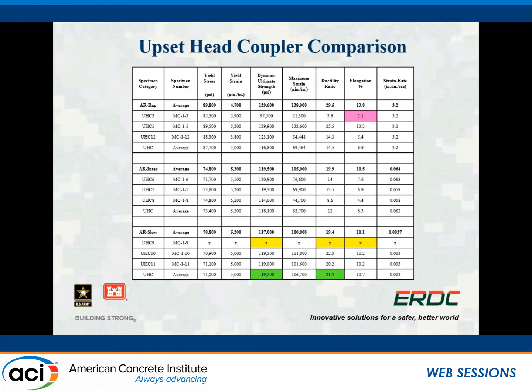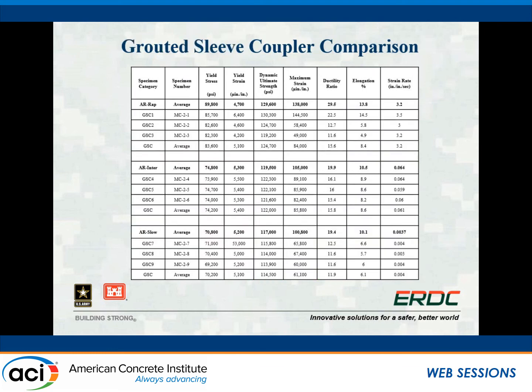Similar for this upset head coupler that we talked a little bit about, we get fairly good performance if we're looking at quasi-static strain rates, but as we step up to dynamic strain rates, those properties are reduced, both the strength and percent elongation. For the grouted sleeve, even though the failures were probably not ideal, did have acceptable properties at all strain rates. We saw tensile strengths and elongations that were acceptable based on the UFC change 1.